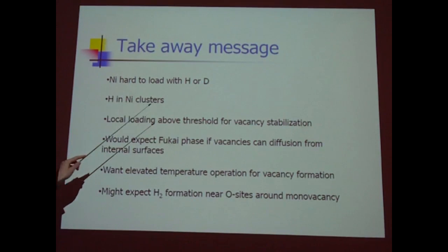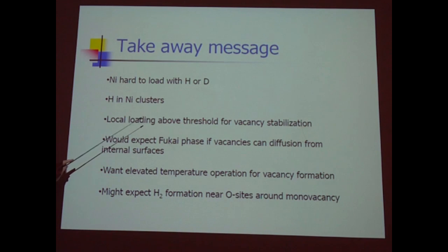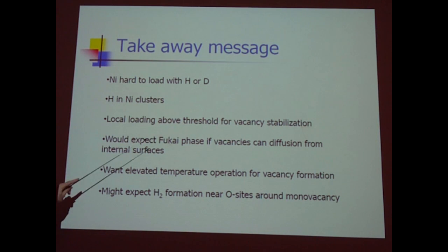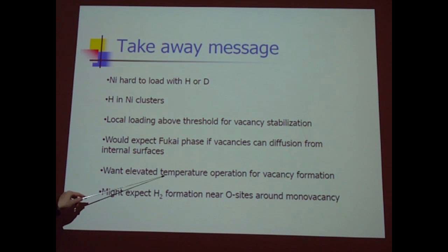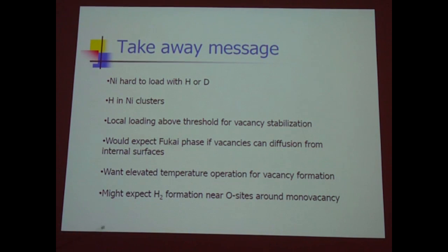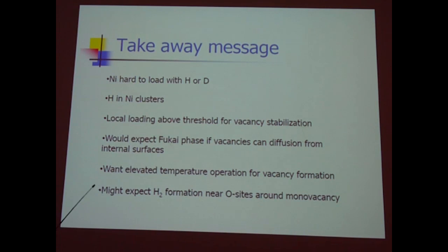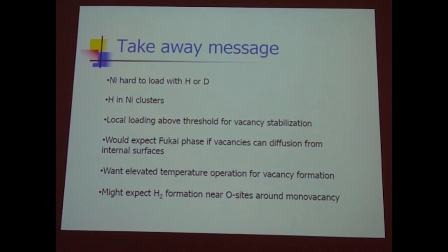So the takeaway message: nickel is hard to load, it clusters, you exceed the loading density for vacancy stabilization once you cluster at all. You'd expect a Fukai phase if you can diffuse from internal surfaces. You probably like elevated temperature in our nickel hydride system in order to encourage vacancy diffusion.